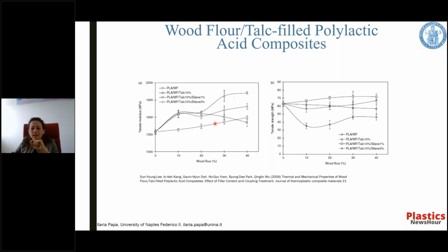As you see in this slide, an increase in Young's modulus was observed in correspondence with an increase of wood flour, while the best performance is obtained with the compound containing the PLA-WF-talc, that is the coupling agent. So the behavior in the presence of the silane improves compared to the compound of PLA and WF only, the neat one. As far as the tensile strength is concerned, the best behavior is obtained for the PLA, WF, talc, and 1% of silane.